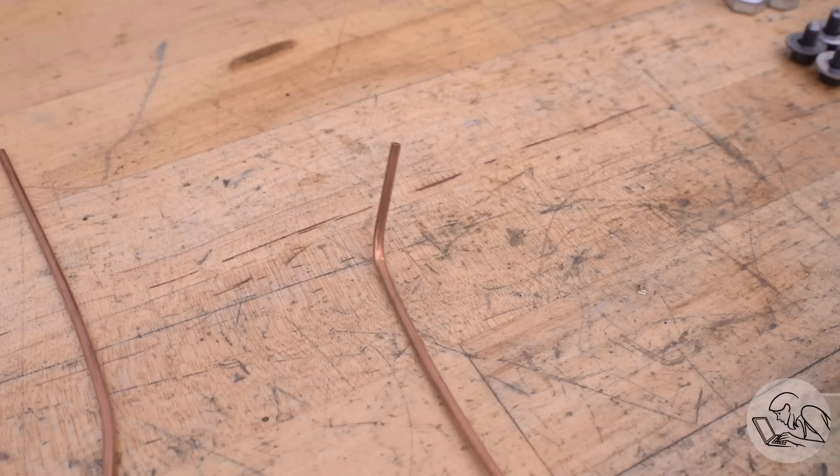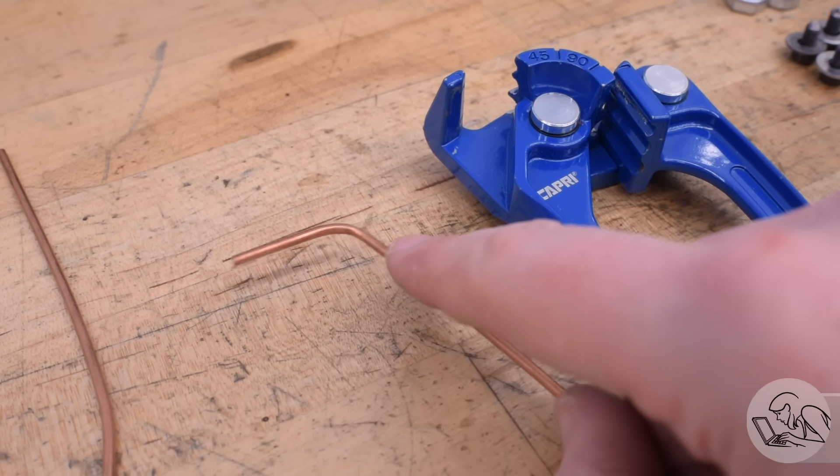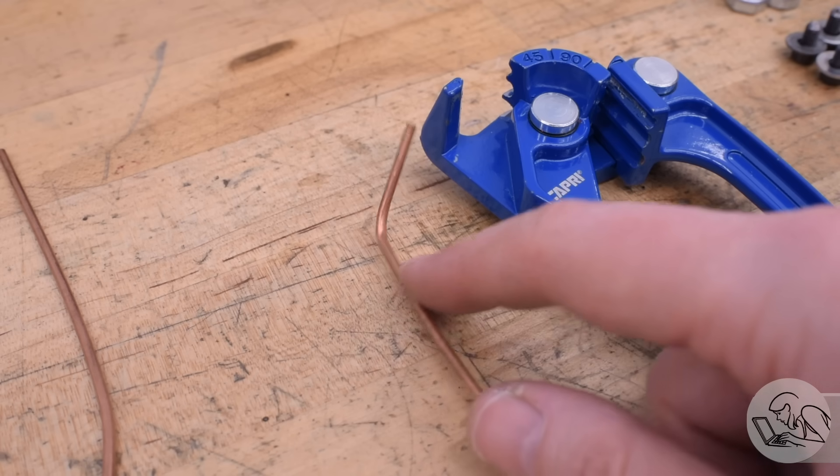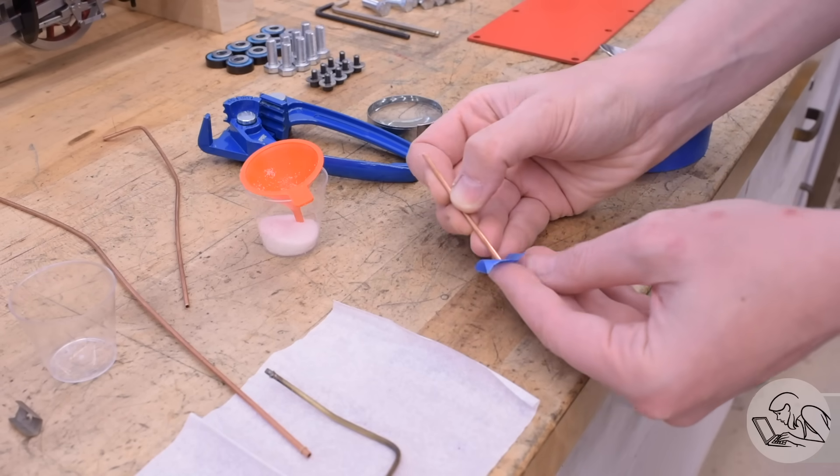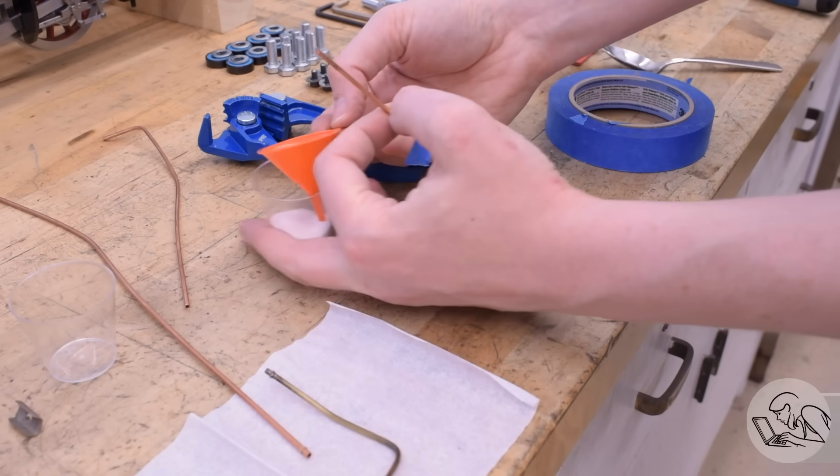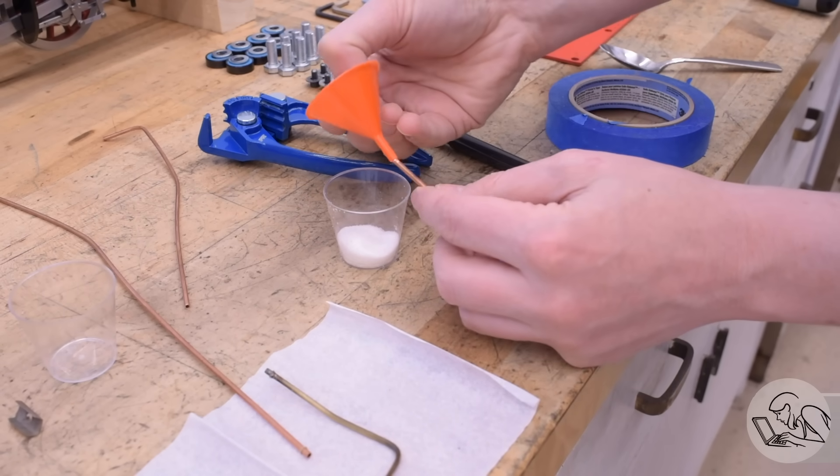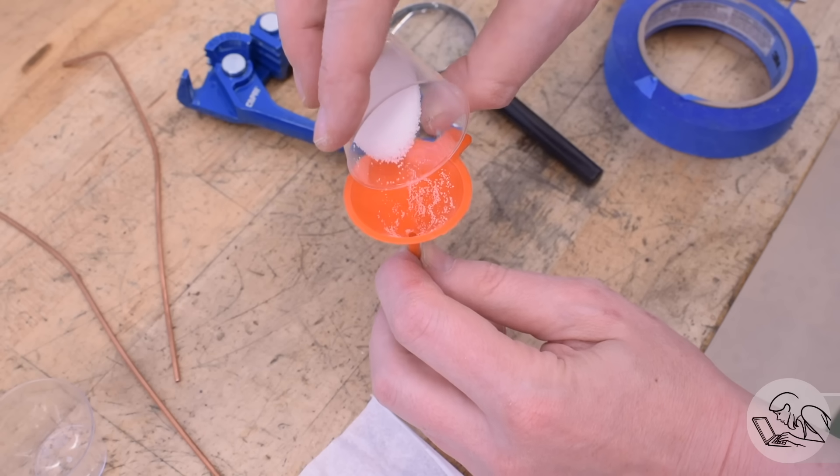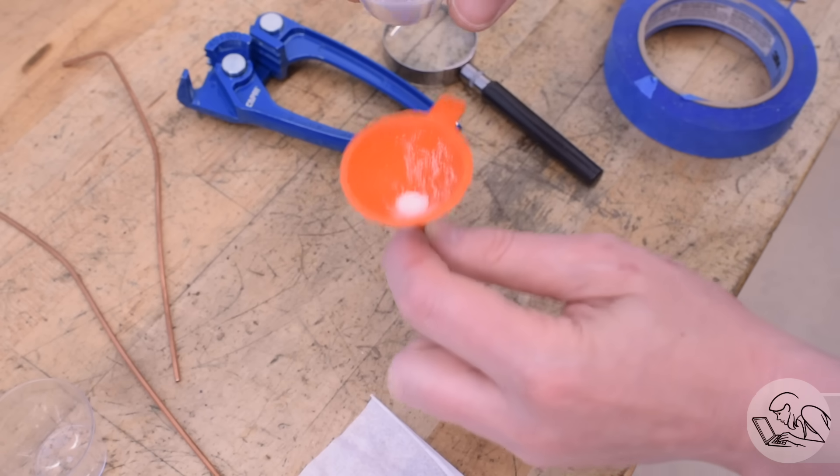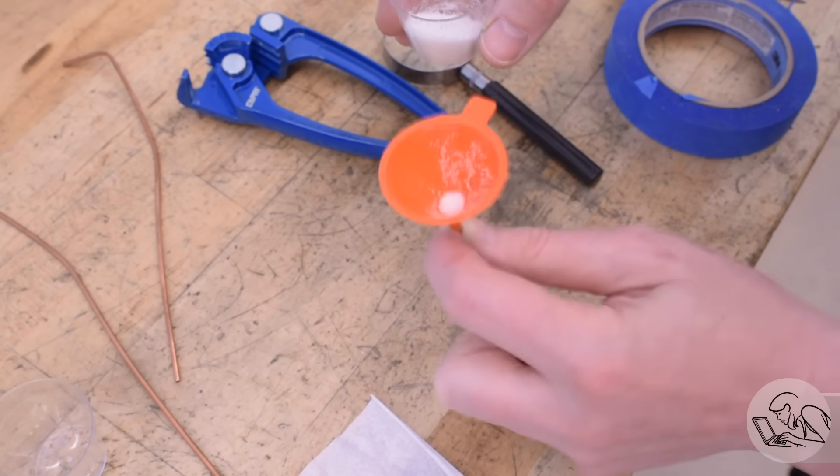Next I had to figure out how to bend this pipe. I tried my standard small tubing bender initially, but this tubing is so small and so thin walled that it kinked even with a tubing bender. The next thought I had was when people bend larger tubing like roll cages in race cars, one of the things people do to prevent kinking is they fill the tube with sand. The sand inside prevents the kink because the tubing can't deflect inward. It forces the tubing to stretch and form a nice constant radius bend.